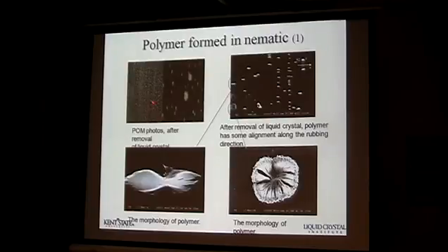Well, if you have a surface alignment, it aligns in the alignment direction, and then it forms a very uniform structure in terms of size. And this is more like microscope pictures, but here is the SEM picture. Well, in some alignment areas, it forms a very, very well organized shape. And these shapes look like either a bow tie or your mustache. And the other one, in the non-alignment regions, it forms more radial structures. It has freedom to go anywhere to minimize the energy, so you can see more of a flower-like shape.